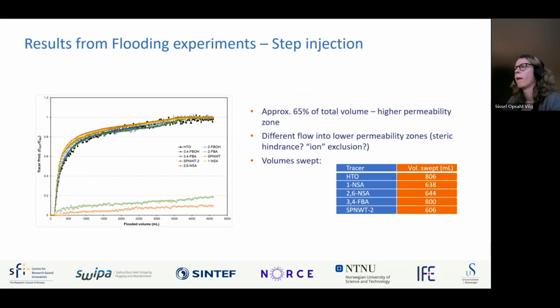So on this slide, you see results from the flooding experiments where we did a step injection. You have the flooded volume on the x-axis and the produced tracer concentration on the y-axis. The dark blue curve here is our reference tracer, tritium-labeled water. And we see that most of our tracers follow the same general trend as the reference tracers. These two here on the other side clearly have deviation from ideal behavior. It's probably close to reversible sorption to the Portland cement.